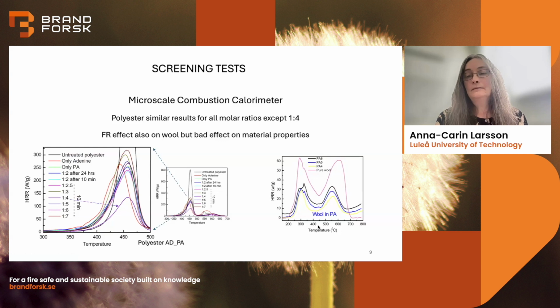Even though wool didn't mix well with the PA, we still wanted to do one test with wool just to see what it looks like. We can see that also on wool, the phytic acid reduces the heat release rate.